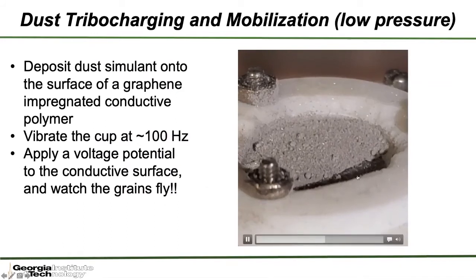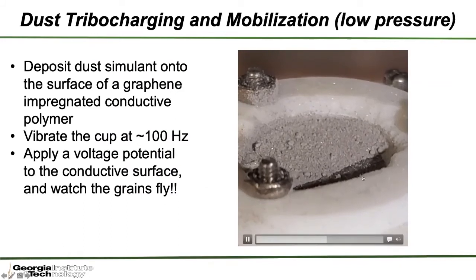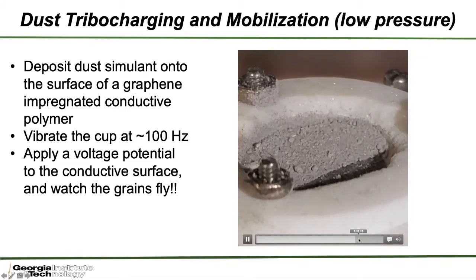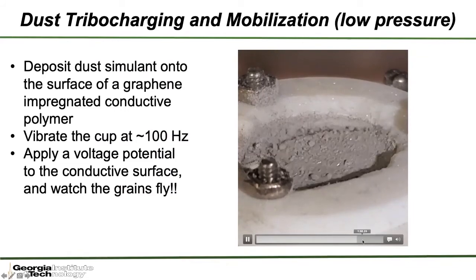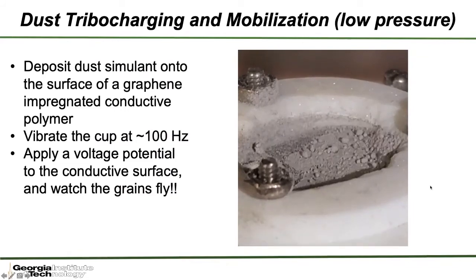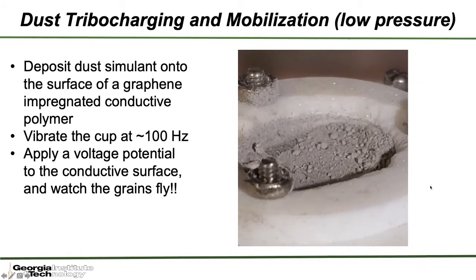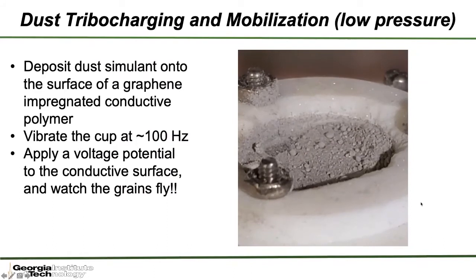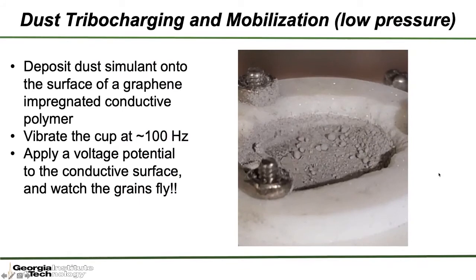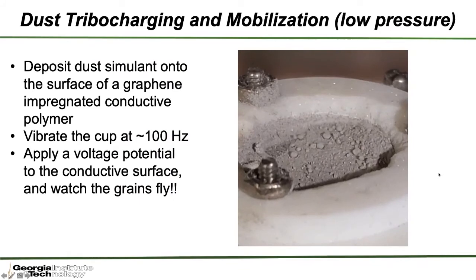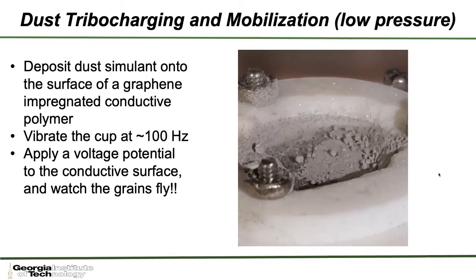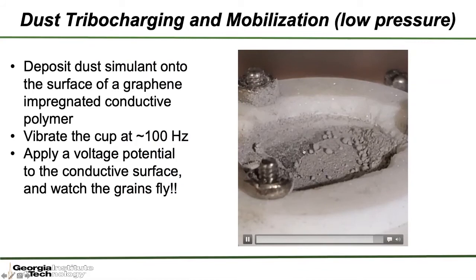And so the cup vibrates along, and I'm actually going to skip forward to where it gets really exciting here. And all of a sudden, we see that some of these grains, there's just a huge reaction, and they fly off of that surface. And so what we're showing is that we're definitely getting this vibratory electrostatic charging of dust grains, but we can also push them off of this surface simply by applying a potential.